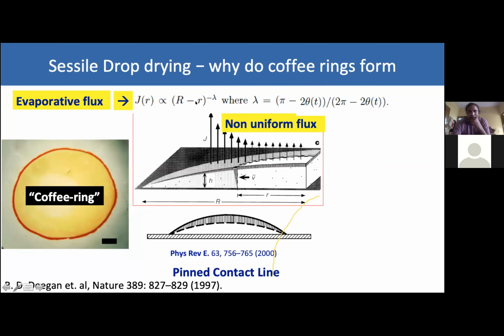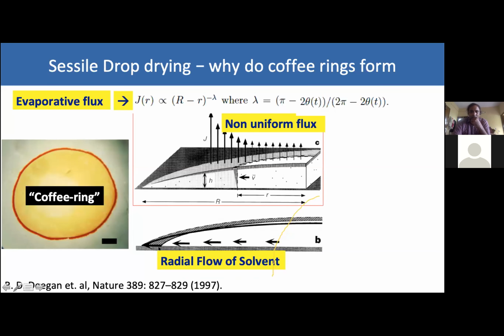If you substitute small r equal to capital R, that is at the edge, it turns out that the flux is infinite. And if you take an example where r is equal to 0, that is in the center, then J of r is proportional to 1 over R. Therefore, you can imagine that the evaporative flux at the center of the drop is less, and it increases as you go away from the center, and it is maximum at the drop edge. So there is more evaporative flux from the edge, and because the contact line has to be pinned, even though there is a higher evaporation of fluid from the drop surface, it induces a fluid flow from the interior towards the droplet edge.